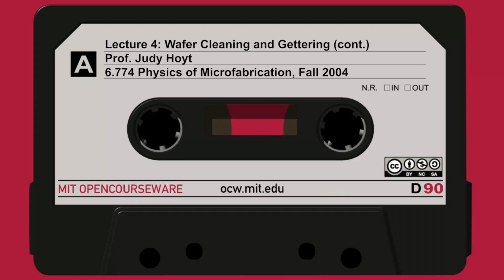So let's go on to slide number 11, and this is a schematic illustration and discussion of the methods of gettering for alkali ions. This is meant to be a cross-section of your wafer, starting here at the bottom in red, the back side of the wafer, and up at top is the front side of the wafer. There's some devices here shown. These little regions are supposed to be p-n junctions, perhaps. And in pink at the very top, someone has put on the wafer a layer of PSG, also called phosphosilicate glass. It's actually an SiO2 layer which has a lot of phosphorus in it, up to 5%. So it's an alloy.